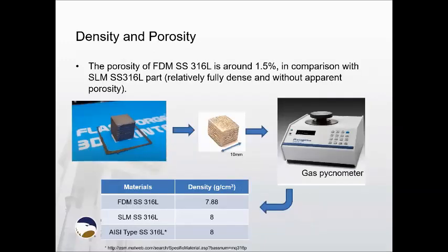Now for the density and porosity, I print small cubes. The cube is about 10 by 10 by 10 millimeter. And after 3D printing, the part is sent out for debinding and sintering, and then it becomes the metal part. Then the metal part is put into the gas pycnometer to estimate the volume. And I use a digital balance to measure the mass of the part, and use the equation to calculate the density. It seems like the density is less than the selective laser melting part and the regular stainless steel 316 part. The density is about 7.88 gram per cubic centimeter. This indicates about 1.5% of porosity.